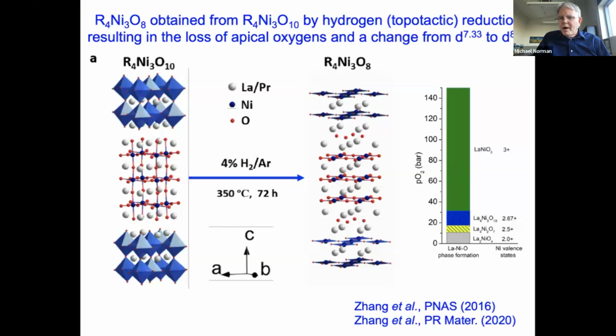On the right, this shows you how these things are grown as single crystals. You basically vary the oxygen partial pressure. You start with a 214 phase. You have a very narrow stability range for 327. This is why in the new 327 work it is very hard to get single crystals. You typically then go to the 4310 phase, and then at high oxygen partial pressure, you end up in the perovskite.